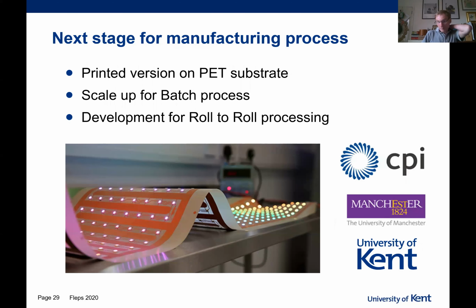Now, the next stage for the project is to consider the scale up. This is essentially a printable electronics project. So we will move from the etched test circuit on Kapton to a printed version on PET, a flexible substrate. And then that will immediately be trialed for scale up for batches of 10 to 15 on a sheet by sheet process. And then moving that on to a continuous roll to roll process, which is available at our collaborators' CPI.